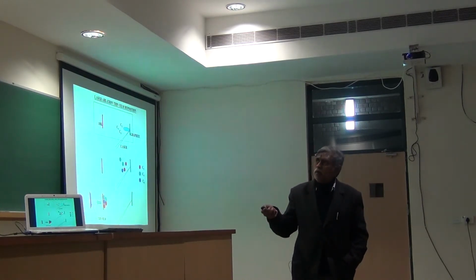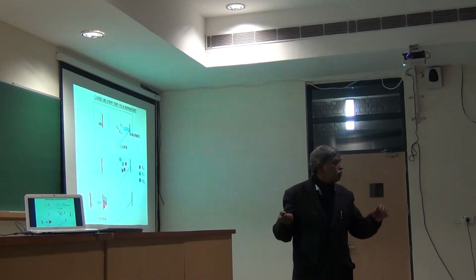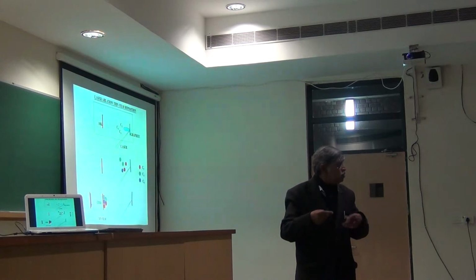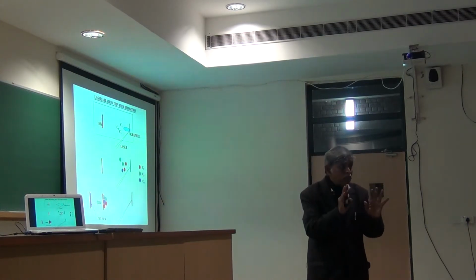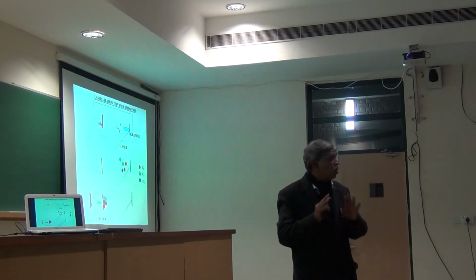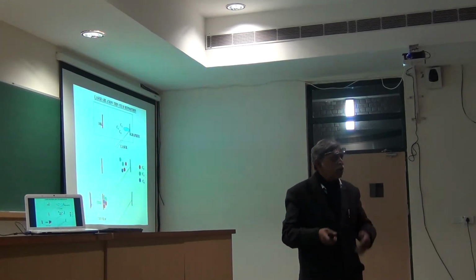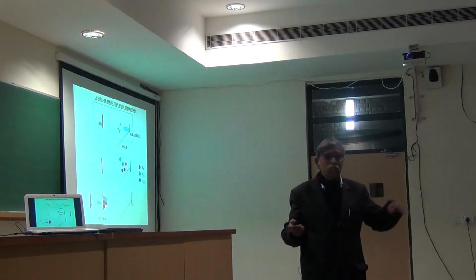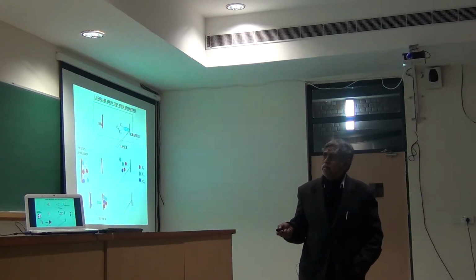So the thin film people don't put the argon on, we put the argon. And we essentially prevent thin film formation of the graphite itself. We basically have all these reactive species that are trapped and kept safe in the argon cage, the argon wall, you may call it. So we can go back and do these experiments on these species. In matrix isolation, this is what we get. In thin film, this is what we get. The white species here are the argon atoms.